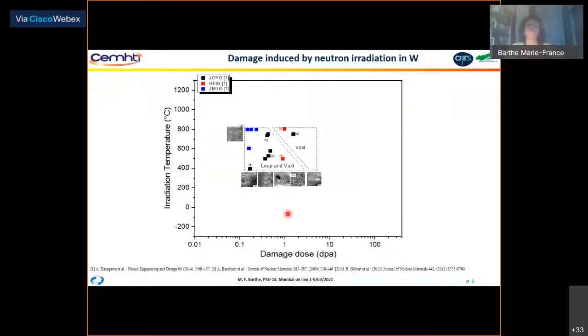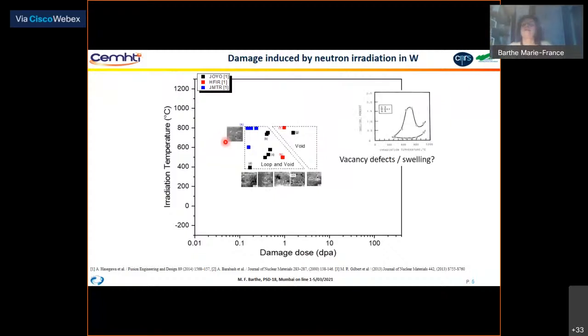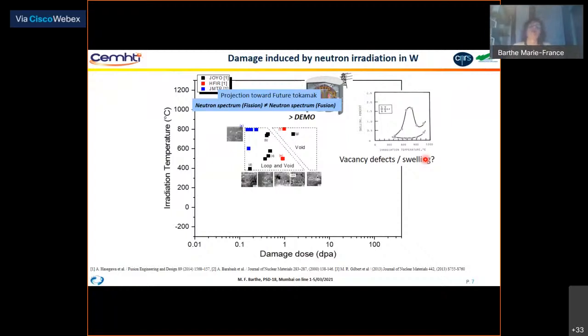And Hasegawa and his co-authors show that loops and voids can be created, and the fraction of voids and loops depends on the damage dose in dpa here and also the irradiation temperature. There are also some old results where the swelling of tungsten has been demonstrated in the temperature range between 600 and 900 degrees C. But the question is how we can project these results towards the future tokamak, where the neutron spectrum will not be the same as the ones in fission reactors.